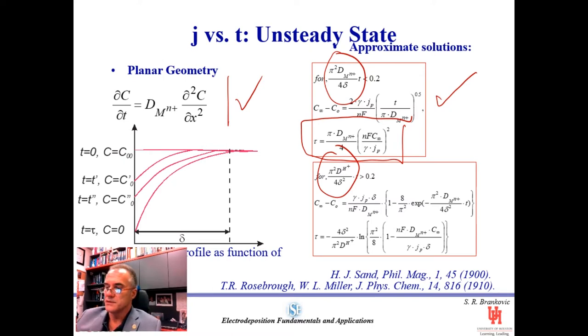You can see that this relation for the transition time is a function of the current efficiency, which typically could be 1 or less than 1 if you have parasitic reactions going on, and the applied current, and it's a quadratic. One inverse of the quadratic function.